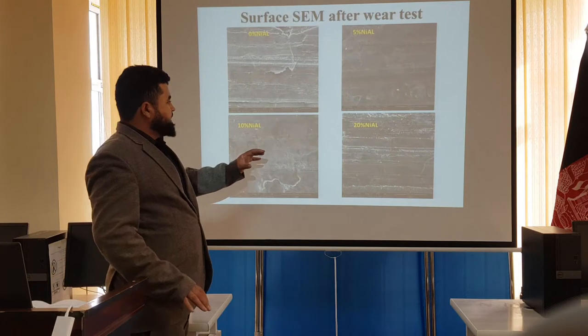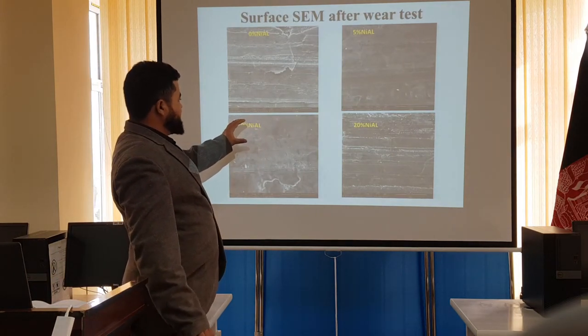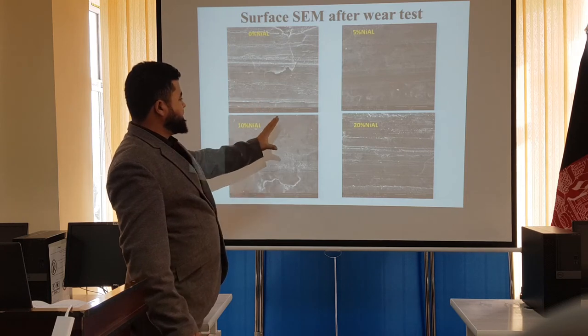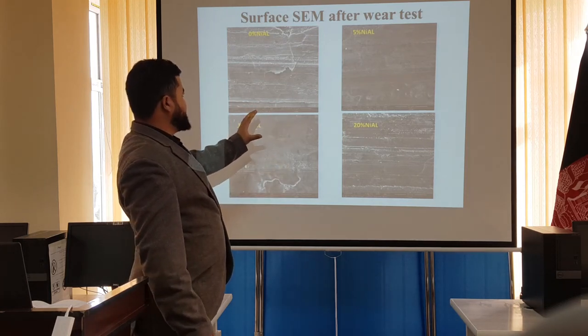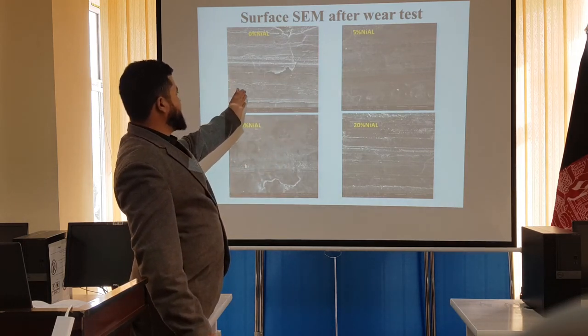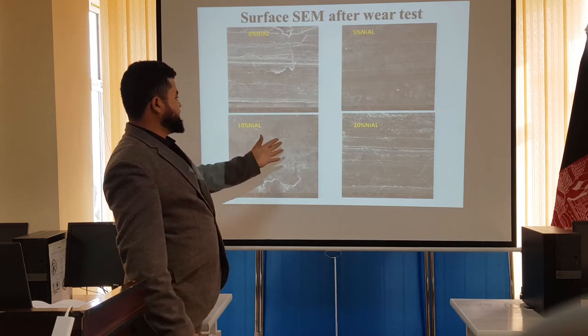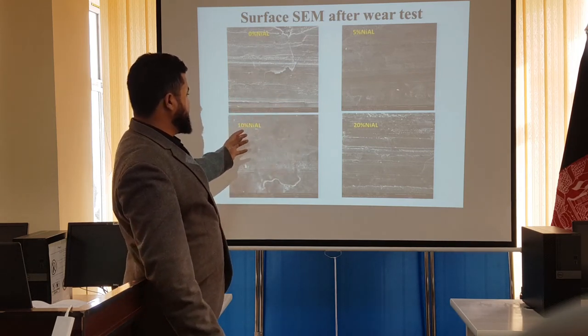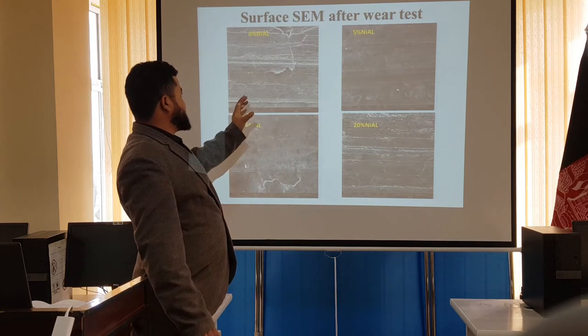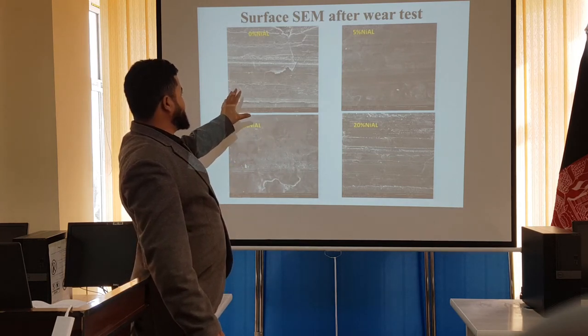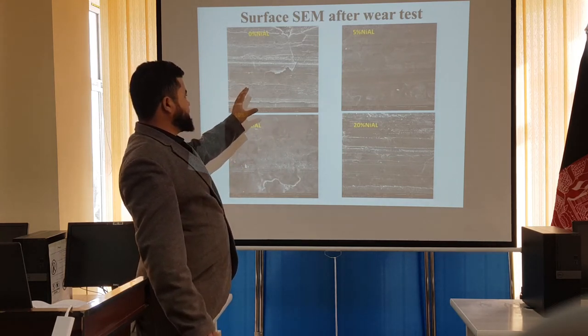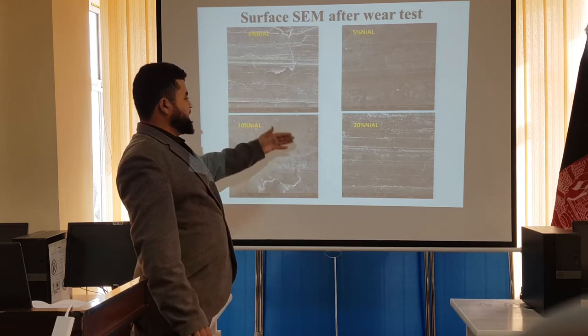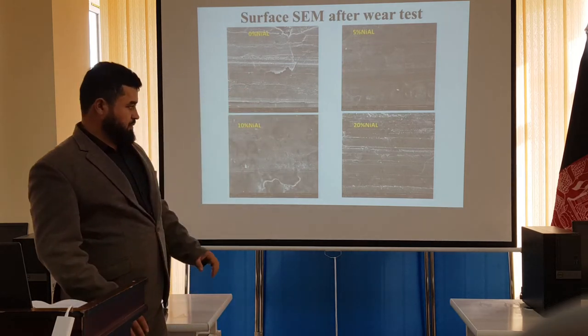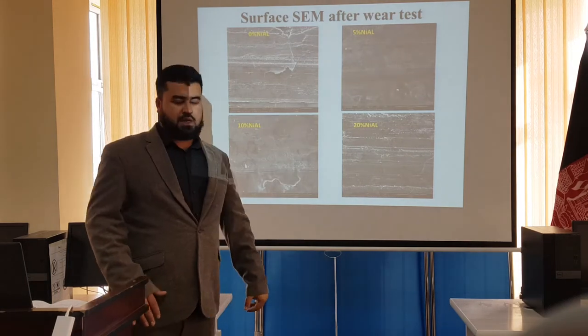Also, we did wear resistance tests. During the wear test, we compared the weight of four samples: 0% nickel aluminum, 5%, 10%, and 20%. During wear, we found that 0%, the 8040 without nickel aluminum, lost much more weight than 8040 doped with 20% nickel aluminum.